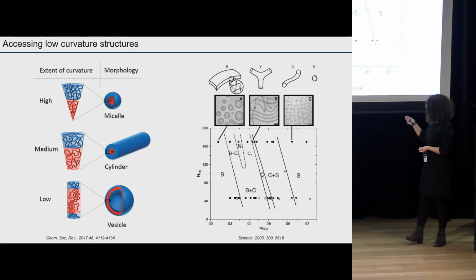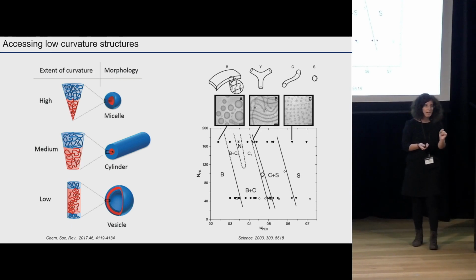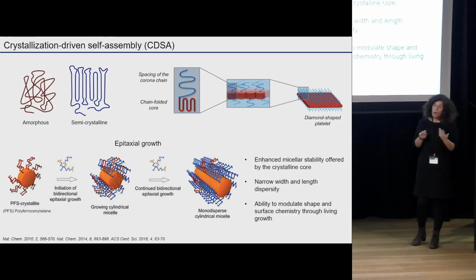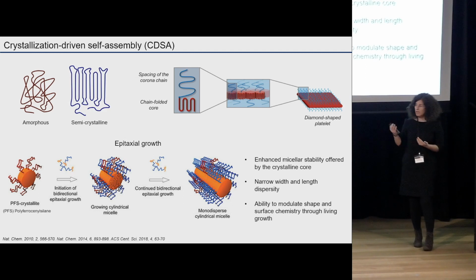And this diagram here shows really that there is a very tiny window where we can access cylindrical nanoparticles of very controlled morphology. So it's relatively easy to get nanoparticles of different morphologies in one pot. So you get a mixture of spheres, cylinders, and so on. But it's not really easy to get just the cylinders, to get specific control over morphology. And one of the techniques that is one of the greatest ones to achieve this is called crystallization-driven self-assembly.